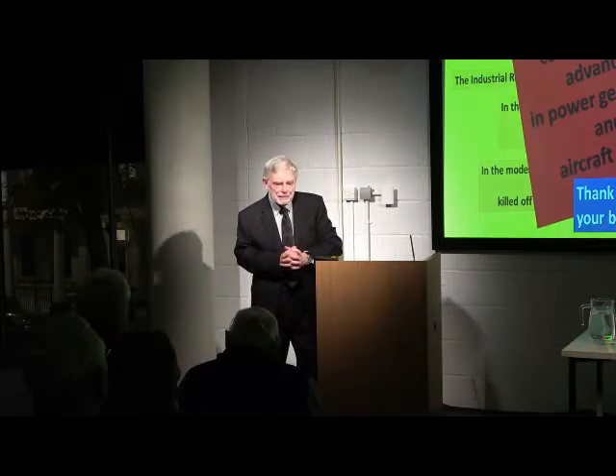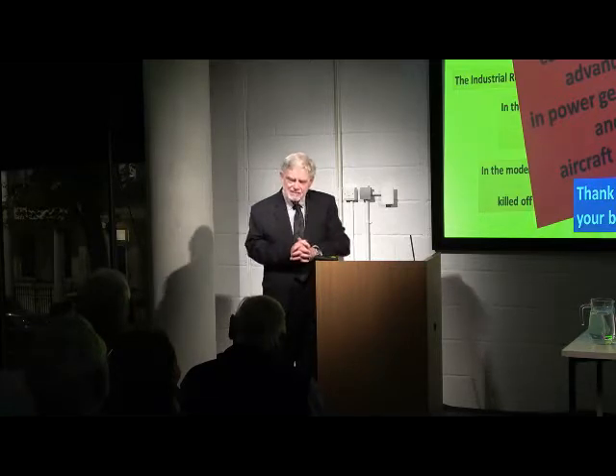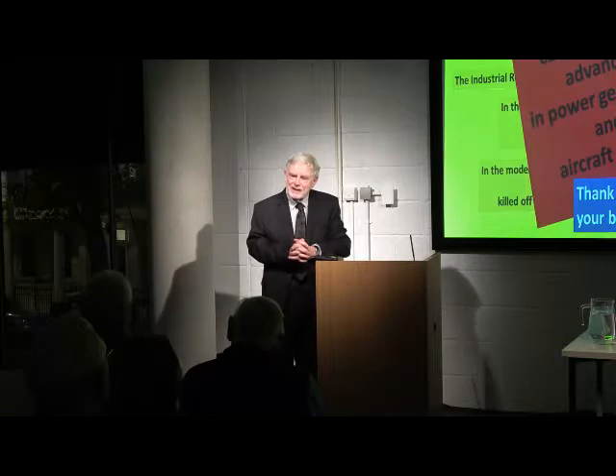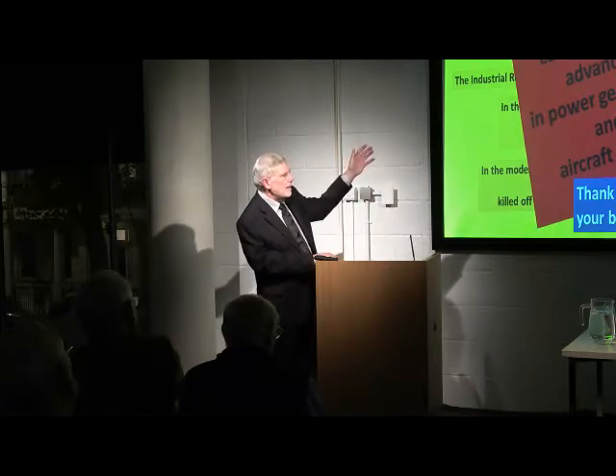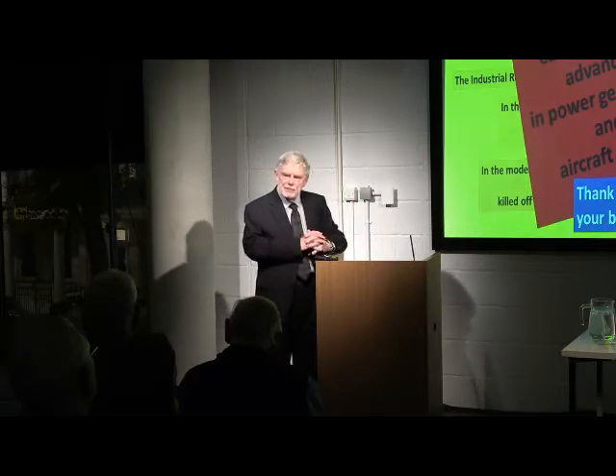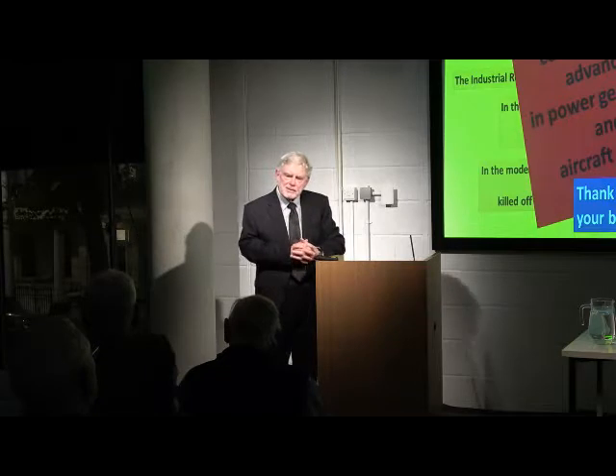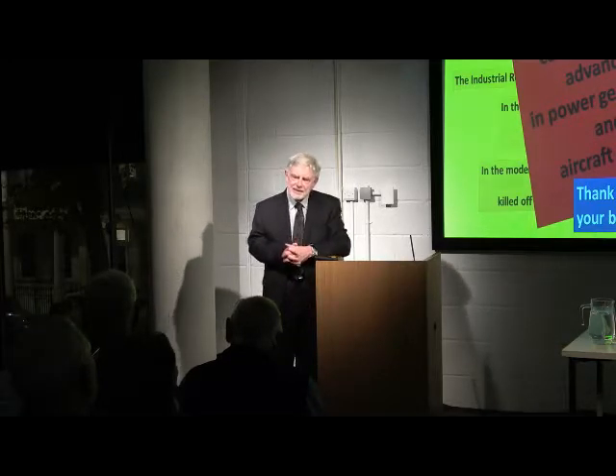But I was also intrigued to see that Rolls-Royce, in this effort to push up the performance of the Rolls-Royce Trent, are looking at silicon carbide fiber strengthened materials. Now, I was telling people about 30 years ago that one of the big problems of silicon carbide is that it doesn't like steam. And when you burn kerosene, particularly at high pressure, as you are in a jet engine, where modern jet engines are running at something like 40 bar pressure in the combustion system, the partial pressure of the steam that's produced is quite high. So you've got a lethal combination of temperature, steam, and silicon carbide.